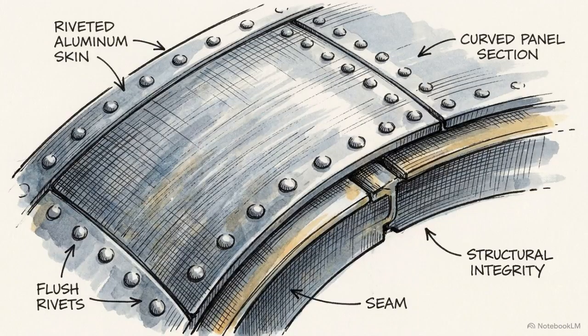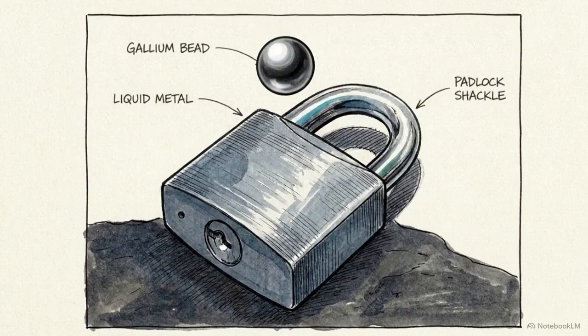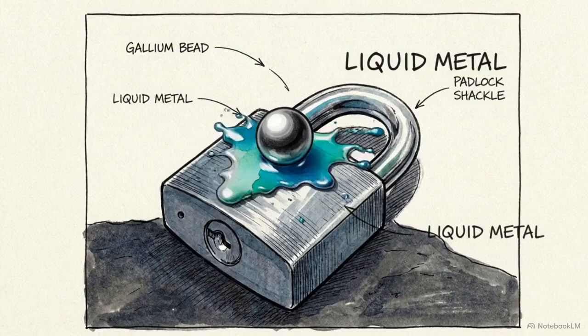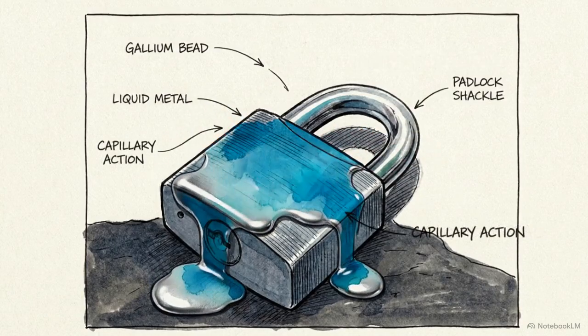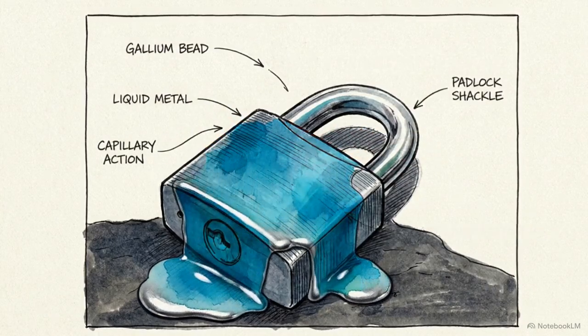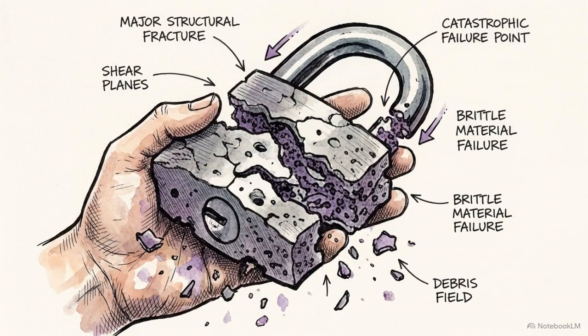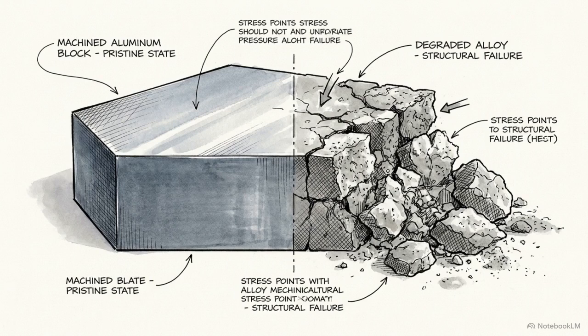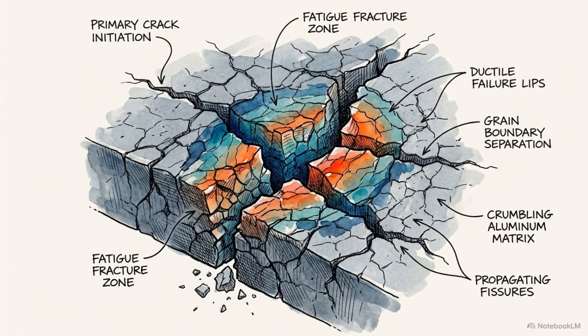Most commercial plane hulls are constructed from lightweight aluminum alloys, materials that are uniquely vulnerable to gallium. If you place a drop of gallium on a solid aluminum padlock or a soda can, the metal begins to fail almost immediately. Within minutes, the rigid structure breaks down and can be crumbled by hand. This safe, room-temperature liquid can destroy the structural integrity of a solid metal object, reducing high-strength aluminum to the consistency of wet chalk. This rapid degradation is a phenomenon known as liquid metal embrittlement.